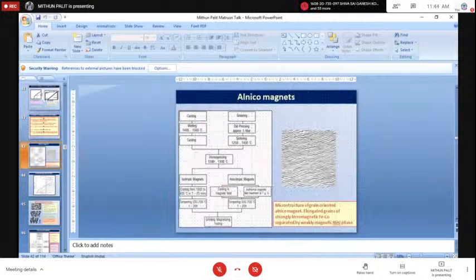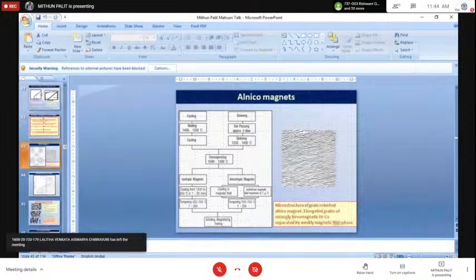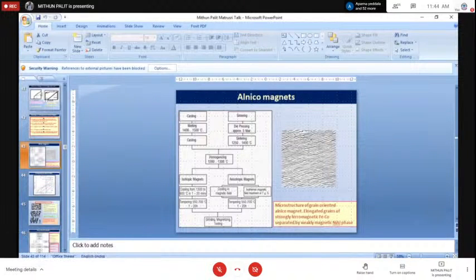Well, I will now briefly describe the different types of permanent magnets and how they are made in my subsequent slides. As I told, the earlier magnets were the alnico magnets. You can see this microstructure. It has very nicely oriented precipitates. These precipitates are the hard magnetic precipitates, and their elongated shape is the source of the coercivity in this alnico material. Alnico material can be made through a melting and casting route, or the powders of this material can be processed through die compression followed by a sintering route.